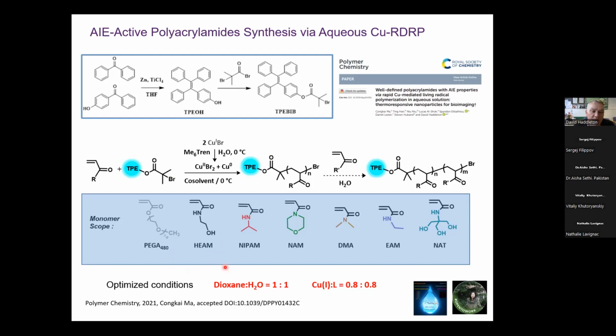You can use acrylates, PEG acrylate, hydroxyethyl acrylamide. This turns out to always be the best monomer. I don't know why, but the narrowest dispersity and the best control you see, even in RAFT actually, in water is with hydroxyethylacrylamide, NIPAM, morpholine, dimethylacrylamide, any of them really.